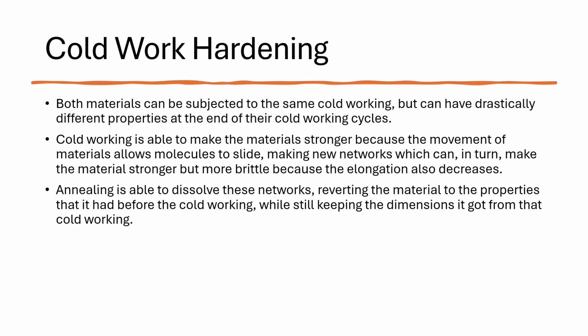And comparing the aluminum to the steel, it had similar dislocation strengthening, but aluminum has a higher stacking fault energy, which makes the dislocations more easily rearranged. So it promotes a dynamic recovery, which makes it harder for it to get harder. So this results in a less dramatic hardening than steel, because steel jumped from around 700 megapascals to almost 900, and then the aluminum went from like 15 ksi to 30, and 15 ksi is roughly 100 megapascals, so it's a lot less dramatic. So microscopic signs for the aluminum would be less pronounced slips and slides, and more equiaxed grains, unless heavily deformed.